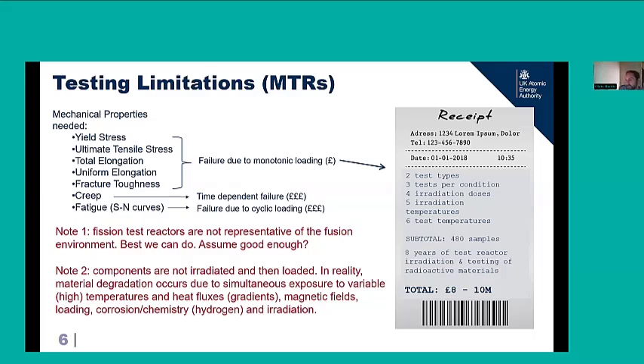So the neutron energies are much lower, and often the fluxes that we can expose materials to are a lot smaller as well. It is the best we can do, but do we just assume it's good enough? The other caveat is that in nearly all nuclear technologies, the materials aren't irradiated and then tested. They are subject to simultaneous loading at temperature, irradiation, stresses, potentially in the presence of magnetic fields, hydrogen, and other corrosive media. So really, these sort of simplified tests only can tell us so much.